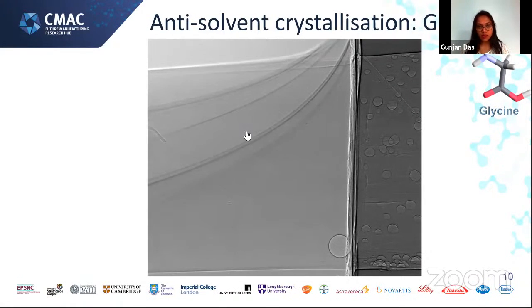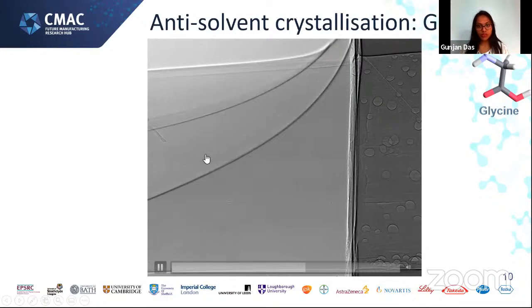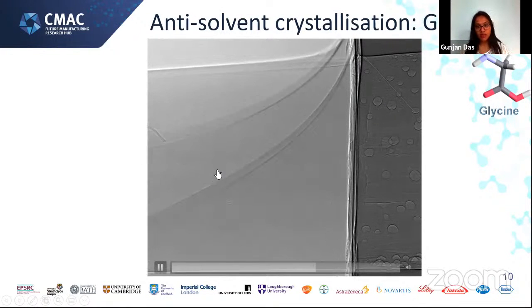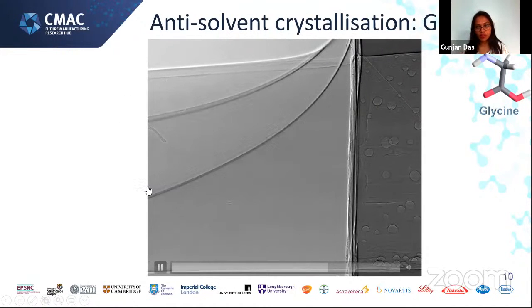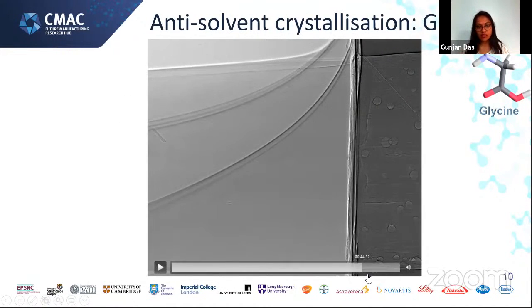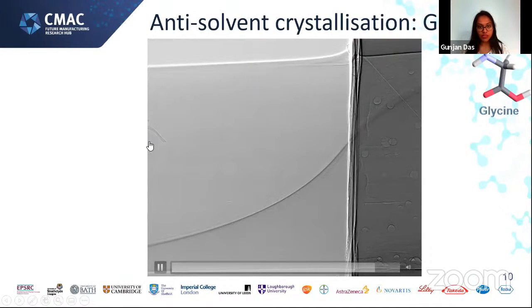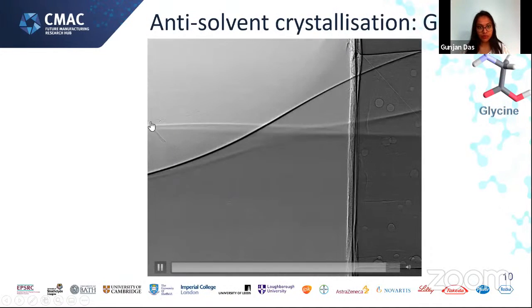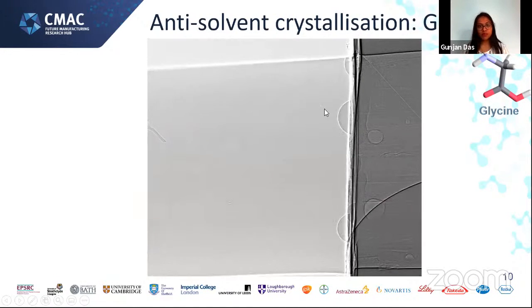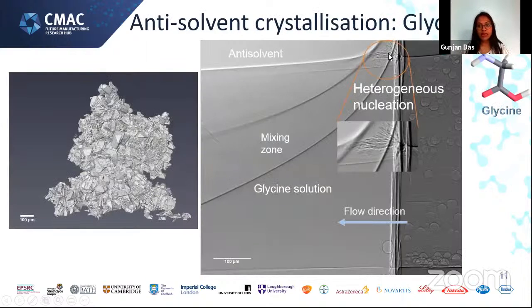What we will see in a minute will be heterogeneous nucleation that will be taking place in this corner of the video. If you look at it now, you also see a lot of mixing, and you can see some crystallized crystals forming towards the end, this right-hand side. So as I've said, this is what the heterogeneous nucleation looked like. Due to the high flow rate, it got flushed down, causing secondary nucleation downstream when we've done some imaging down there as well.